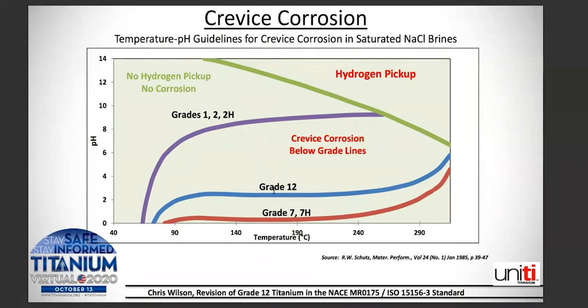If the pH levels are even lower than that, pH level 1, then there would be the availability of grade 7, grade 7H palladium grades that would be able to handle that environment. I did not include the ruthenium grades on this chart, just simply because the availability in the market is not prevalent.